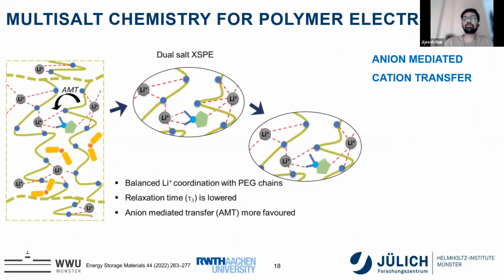And one of the interesting factors for us is why the polymer electrolyte is improving all these ion dynamics within the system. We understood that the anions, what we are adding, secondary or tertiary anions, can act as a mediator, and this can improve the ion transport. So it is a mediation. It can act as a mediator between 2 polymer chains.